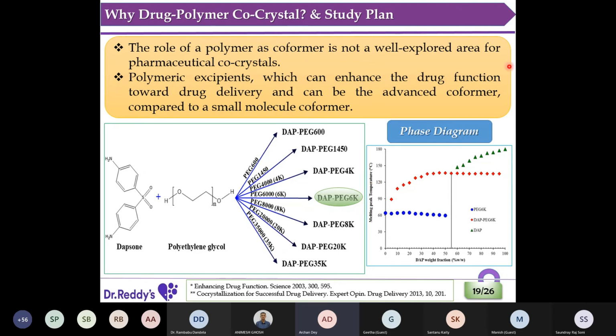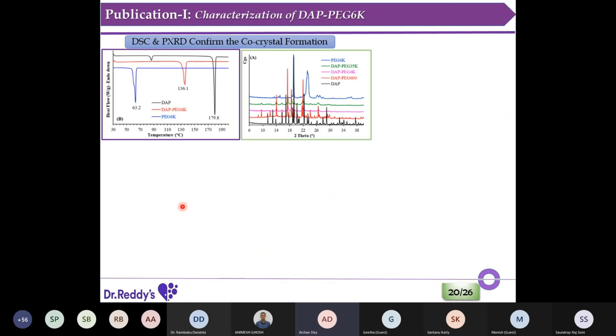In the phase diagram, what we can see is that at the beginning, up to 50%, we can see the presence of the new form as well as the PEG, and above that we can see the binary phase of the new form and the PEG, but around 55 we see a pure phase. That we have characterized by the DSC. So you can see this is the starting PEG melting point 63, Dapsone melting point is 180. So it's coming mostly somewhere in between. So it's very surely confirmed that it is a co-crystal form.